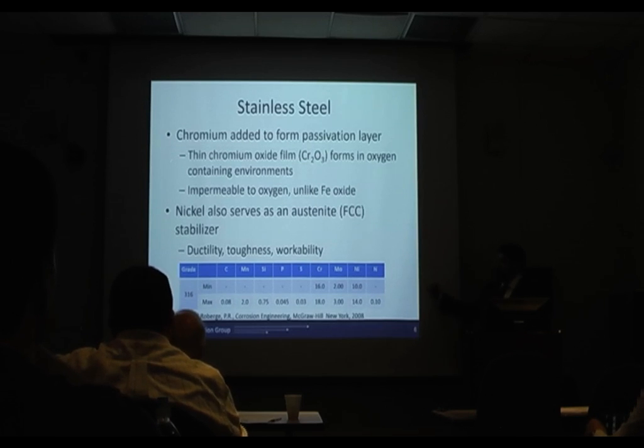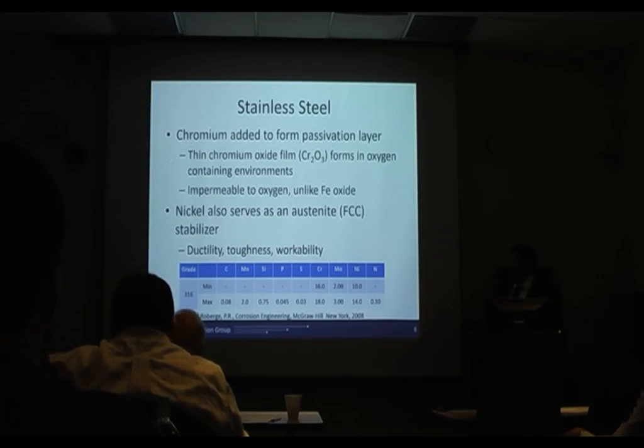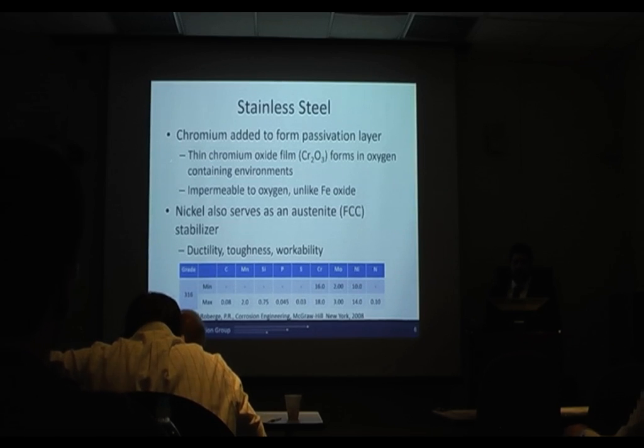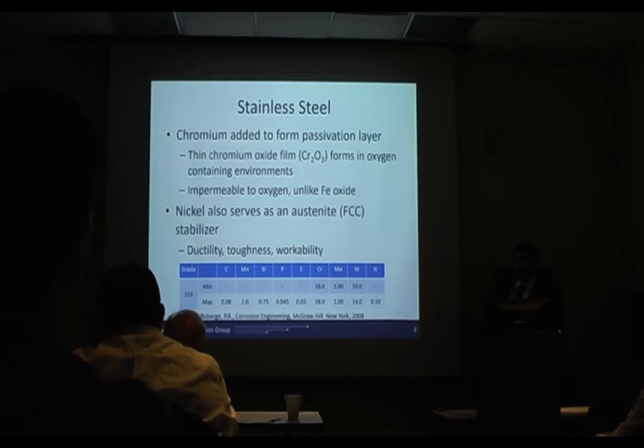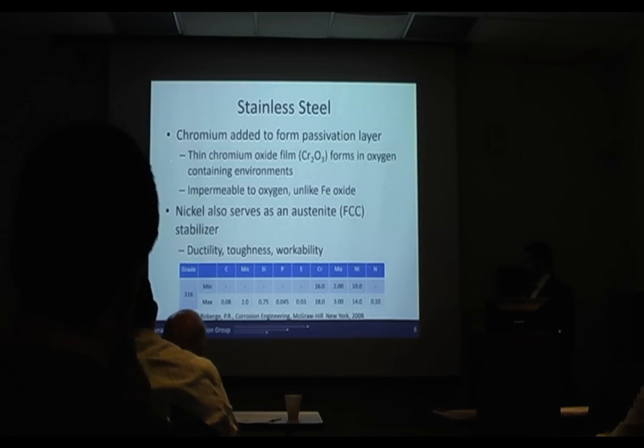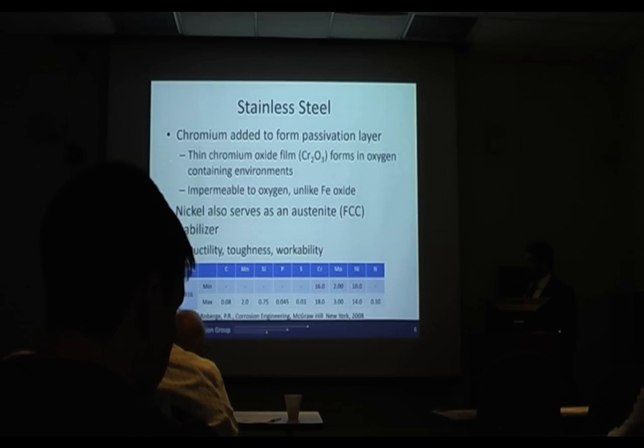The composition range for 316 is shown below, and the big thing to note here is it's 16 to 18% chromium, 2 to 3% molybdenum, which is different than 304. That doesn't have any molybdenum in it, and nickel is 10 to 14%. Note that the 14% is the upper limit of this range, which will be important later.